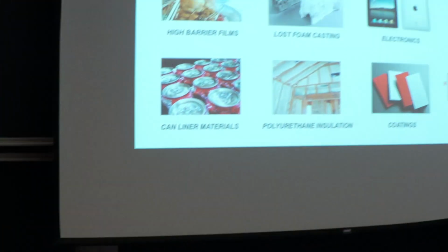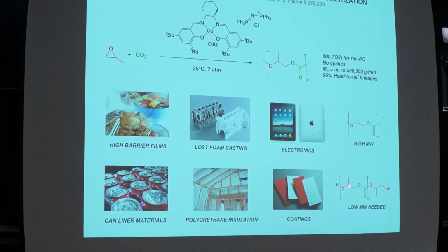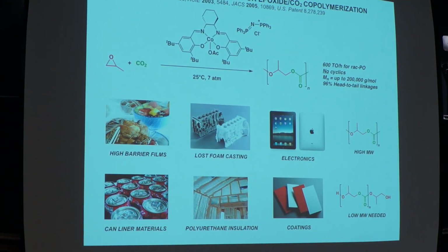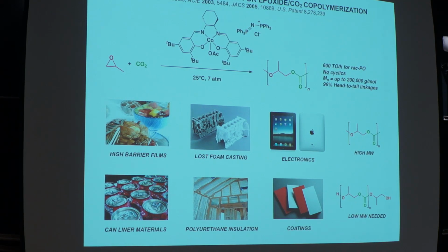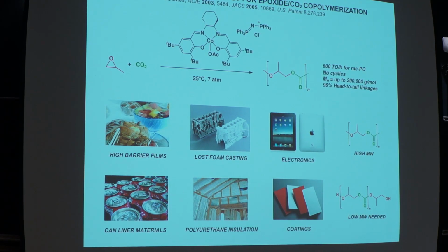Polyurethane insulations, polyurethane. You're sitting on a polyurethane seat cushion, same thing in your automobile. So polyurethanes are really important, and this whole field of architectural coatings. To make these, what you need is a polymer that's lower molecular weight, and on the ends of the polymer are these alcohol end groups. So you can throw in a diisocyanate, and by old-fashioned step growth polymerization, you can build the polyurethane.